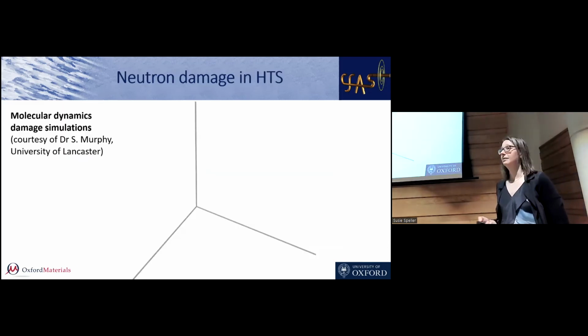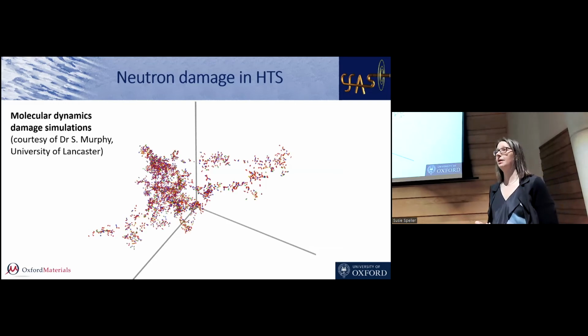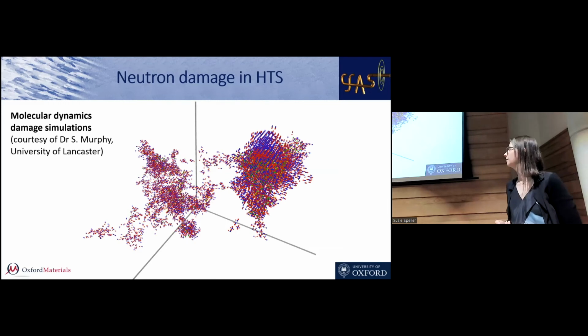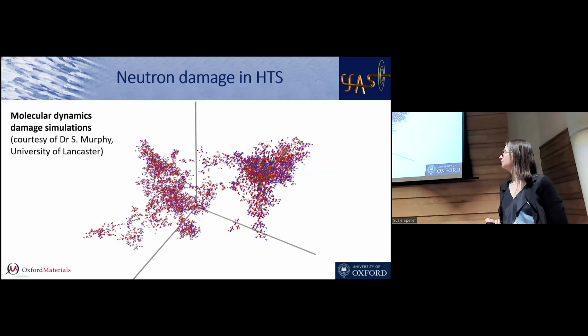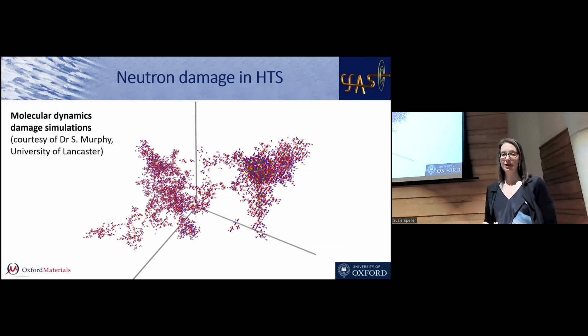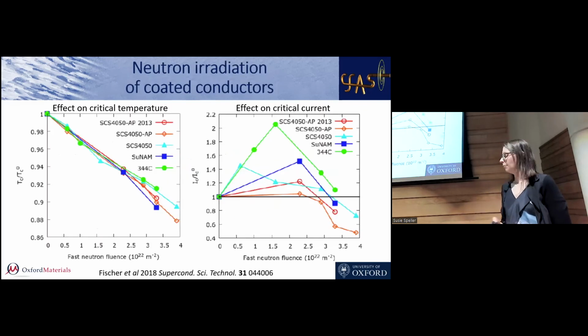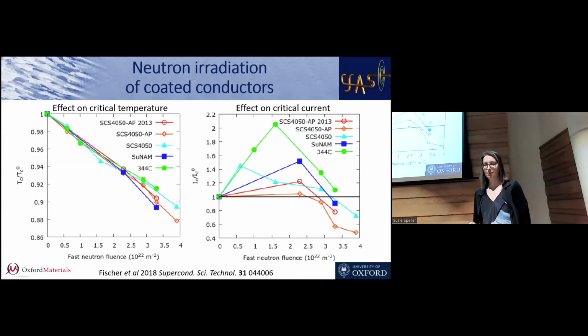And that's bad. So if we look at what happens, this is a simulation of what happens in YBCO when you hit it with a neutron. Everything that you see in a color is an atom that's been moved out of where it should be and is no longer sitting where it should be in the crystal. And you get these sort of regions of damage where the crystal's all been messed up. What it does to the properties is it brings down the critical temperature as we damage it, and it does something interesting to the current. It gets a little bit better first, and then it gets worse.